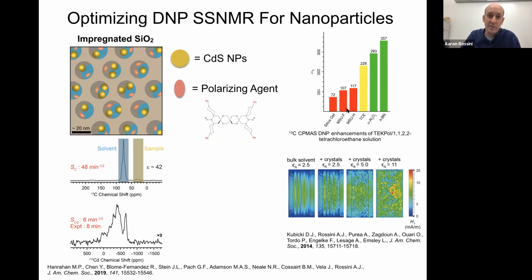And we think part of the reason for that is because silica doesn't have favorable dielectric properties. It's lossy in the microwave region and it has a low real dielectric constant. So the idea we had was, if we have to put in a material to disperse our nanoparticles to do the DNP experiment, let's at least put in something that has good properties for DNP.